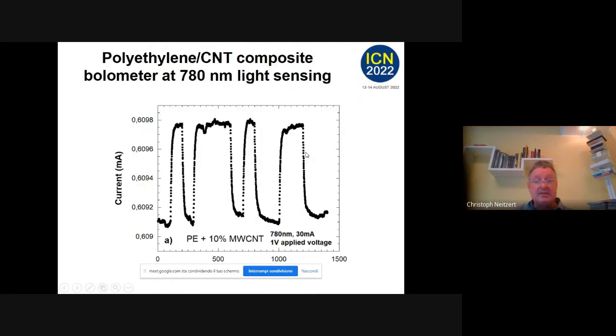We have quite a good dynamics on that. And 1550 and 1720 start to become noisy. That's maybe a problem. But in some range, we get an acceptable bolometer. Here again, we see something which we often find with carbon nanotubes. You see spontaneous changes like random telegraph noise. You have a lot of concentration, but you don't have a lot of percolation paths. Maybe you have 50 percolation paths or so, or 20. And then if one of them is changing, is attached or not, you see switching in discrete steps. So that is the problem in this kind of device, which we didn't find for the polystyrene.